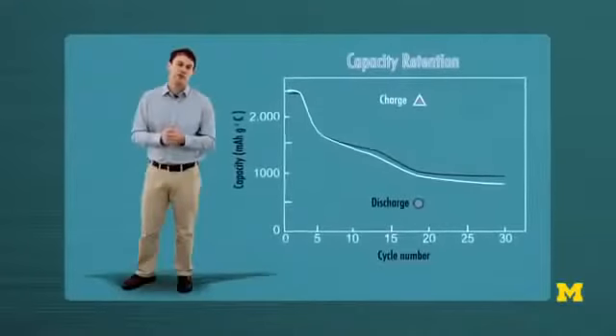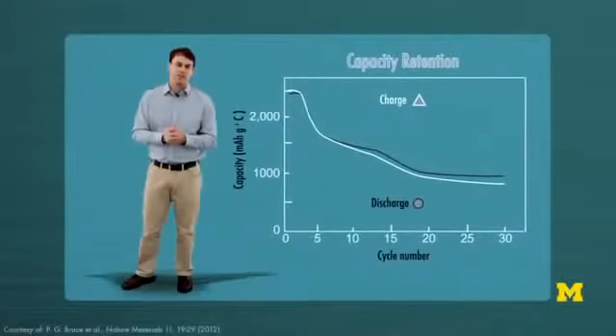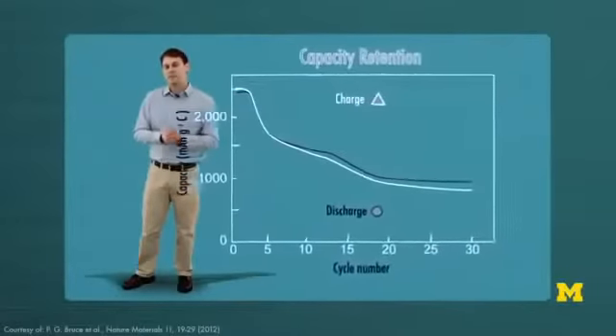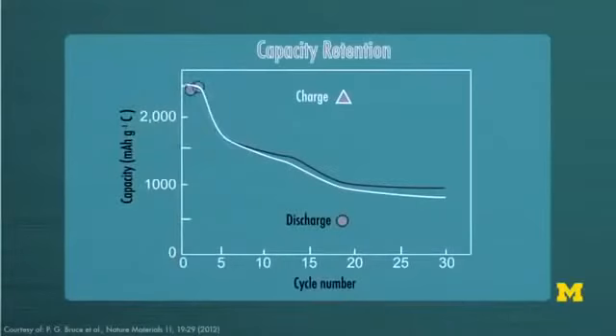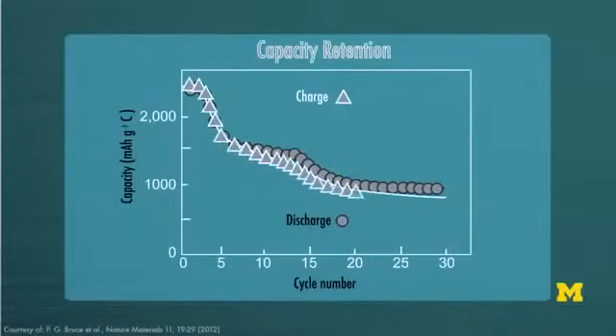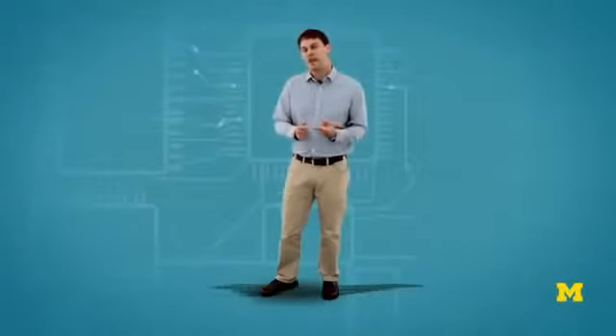A second challenge is shown to the right, and that's capacity retention. So in this case, we're plotting the capacity as a function of cycle number. For early stages in the cycling process, maybe the first few cycles, we get a very high capacity, but then that falls off over time. And here again, there's some debate as to what's the mechanism responsible for this capacity loss. One possibility could be that when we form this peroxide or this oxide phase, that's an insulating film that prevents electron transport from occurring in the cathode. So basically the battery would shut down after that film gets beyond a certain critical thickness.